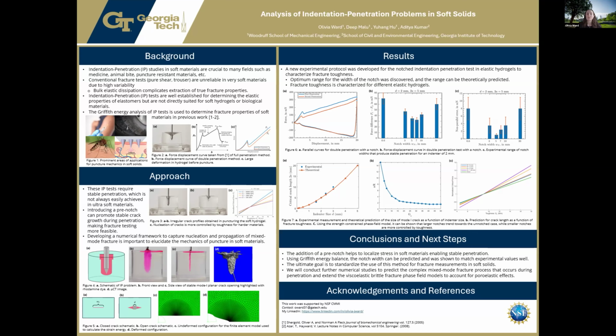In conclusion, this work makes 3 main contributions. First, we propose a modified indentation penetration test using a pre-notch to achieve stable crack growth in soft materials. Second, we showed that the optimal notch size can be predicted theoretically and computationally using energy balance principles. And third, we demonstrated that this method can be used to reliably characterize fracture toughness in soft hydrogels.